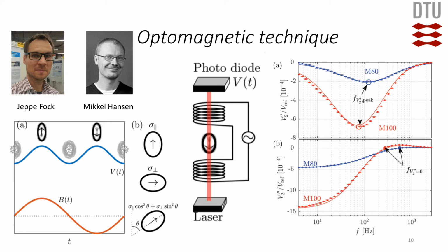The dipoles of magnetic nanoparticles will align to the field in both cases, just in the opposite direction, but from the optical point of view, it doesn't matter. In both scenarios, light will go through. Whereas at zero magnetic field, the particles are randomized, their orientation is not aligned, and they block light.